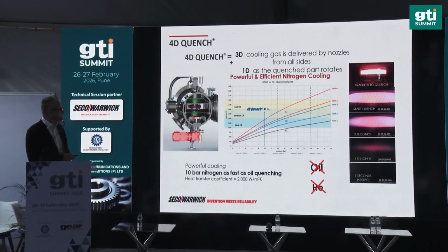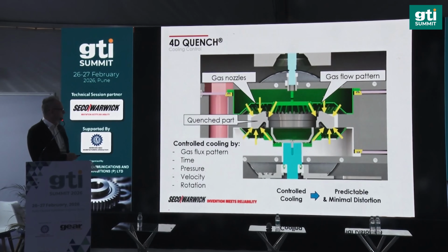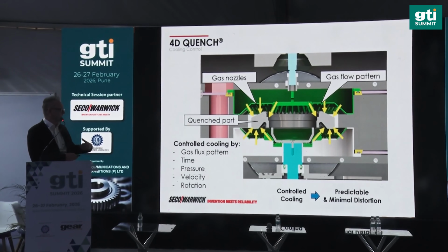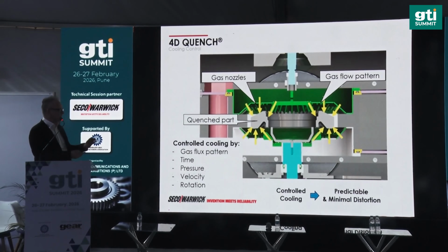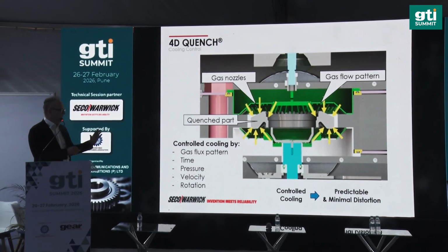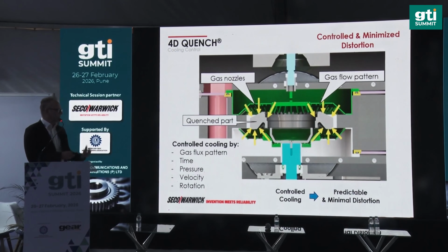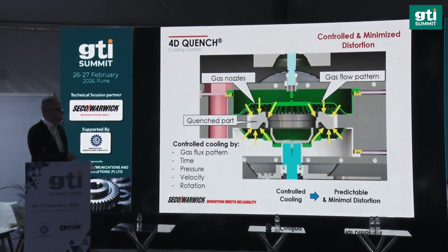So where we are with this solution is that if we come across a single piece element for hardening, we don't need so much high pressure, but utilizing high pressure gas quenching, of course, giving you all the benefits, you can utilize 10 bar nitrogen quench and be as fast as oil quenching. Yeah, so we don't lose anything in these terms. And by designing the quenching module dedicated for a particular shape of the part, we can optimize the level of distortion after the heat treatment.